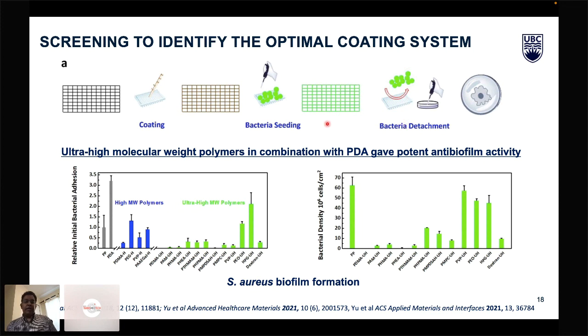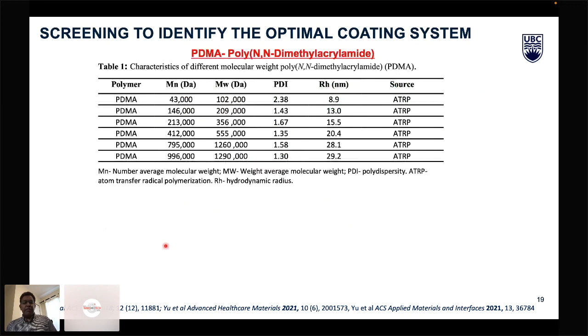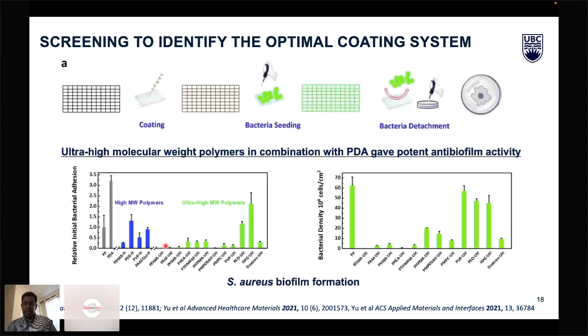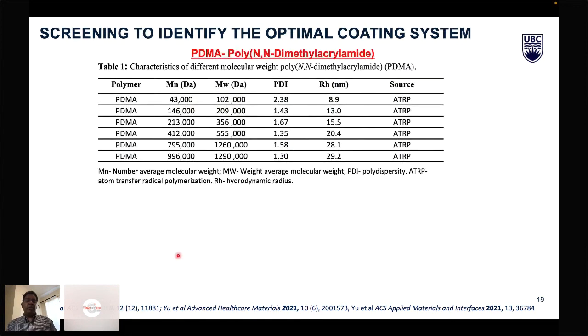So in this coating process, or this screening process, we identified that we could utilize low molecular weight polymers, as well as high molecular weight polymers, as well as ultra high molecular weight polymers. And what we found is that some of the ultra high molecular weights, such as PDMA, polydimethyl acrylamide, show very little bacterial adhesion in this binary combination coating. So we identified that polydimethyl acrylamide was one of the good candidates.